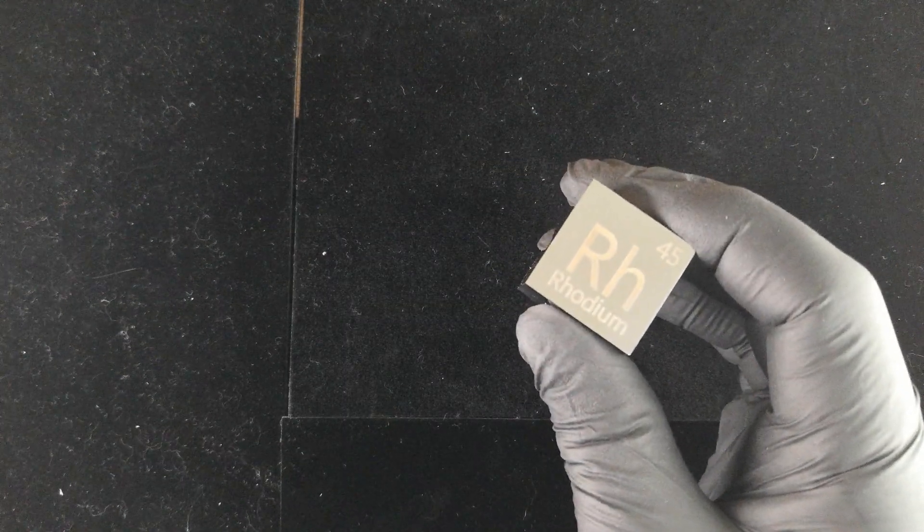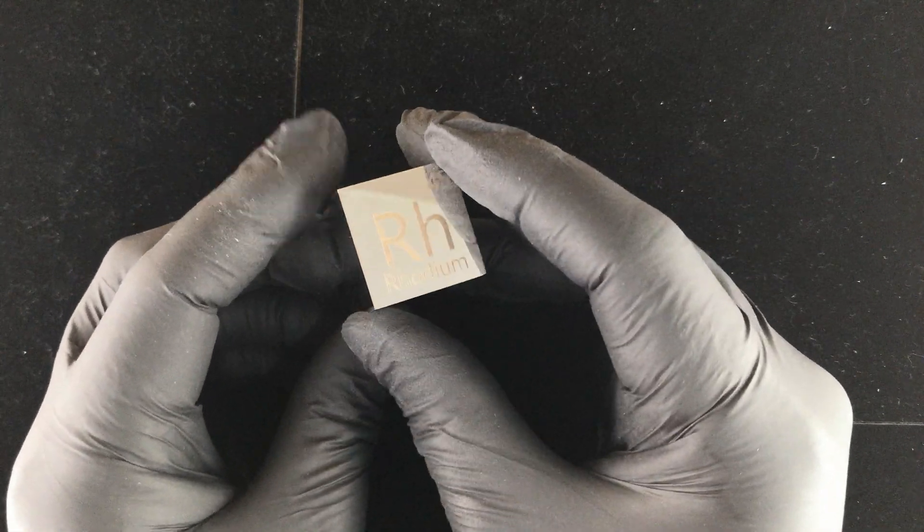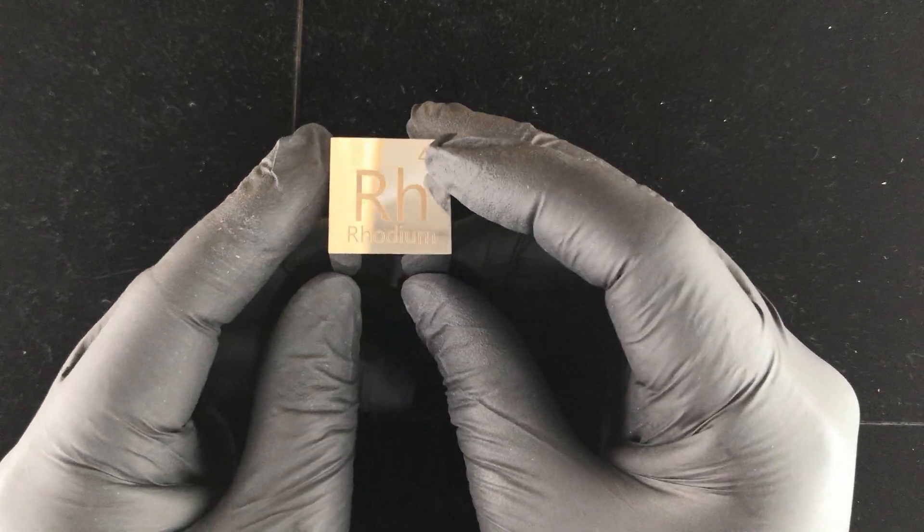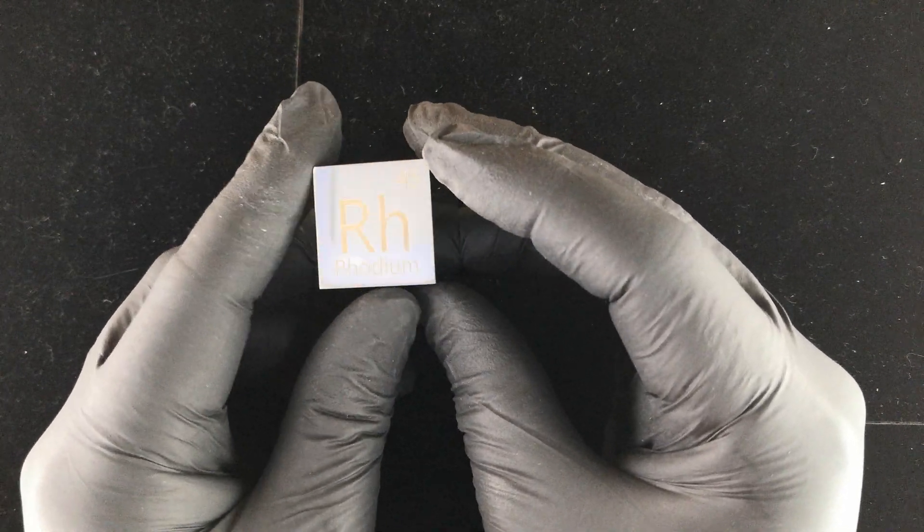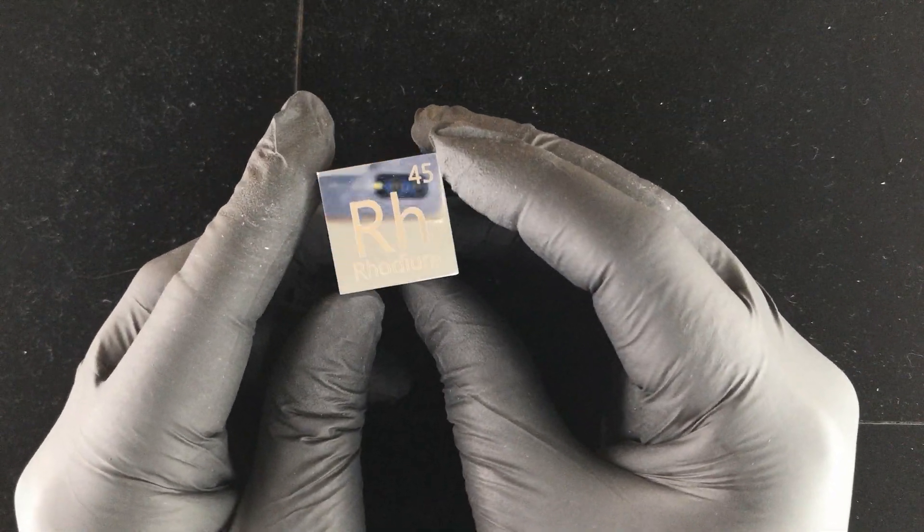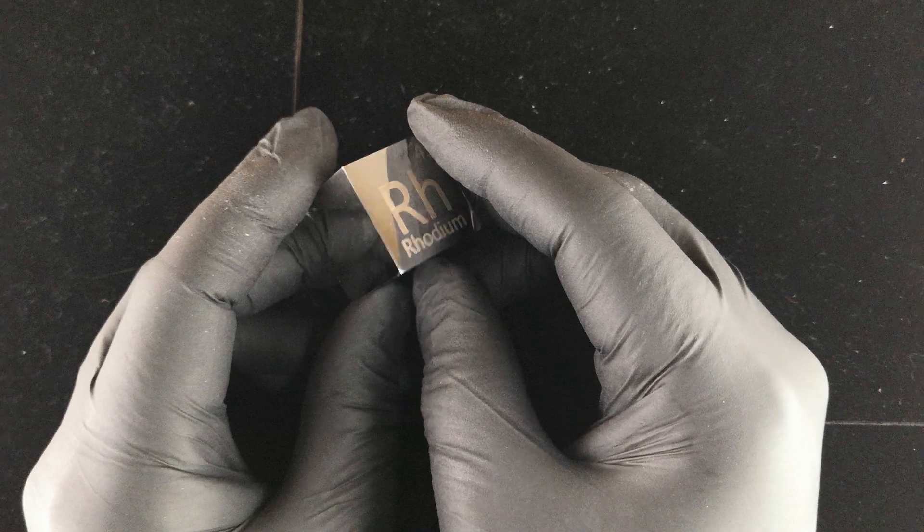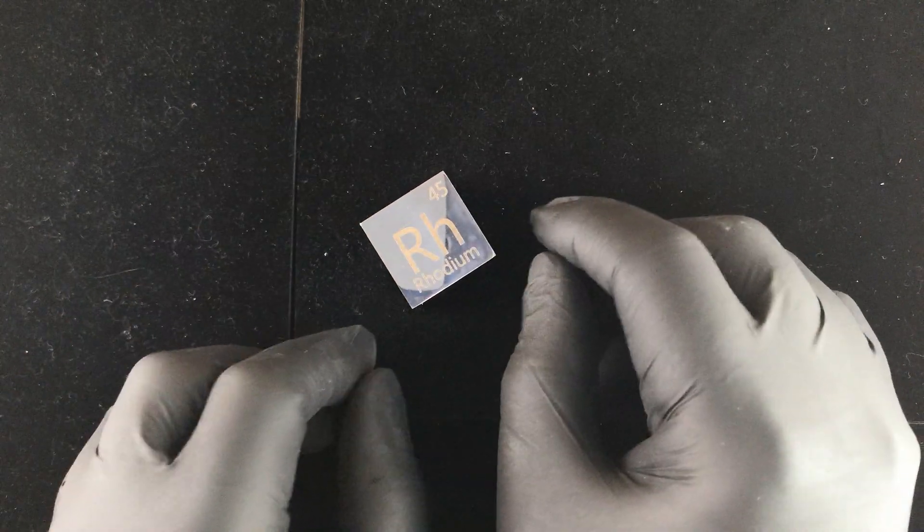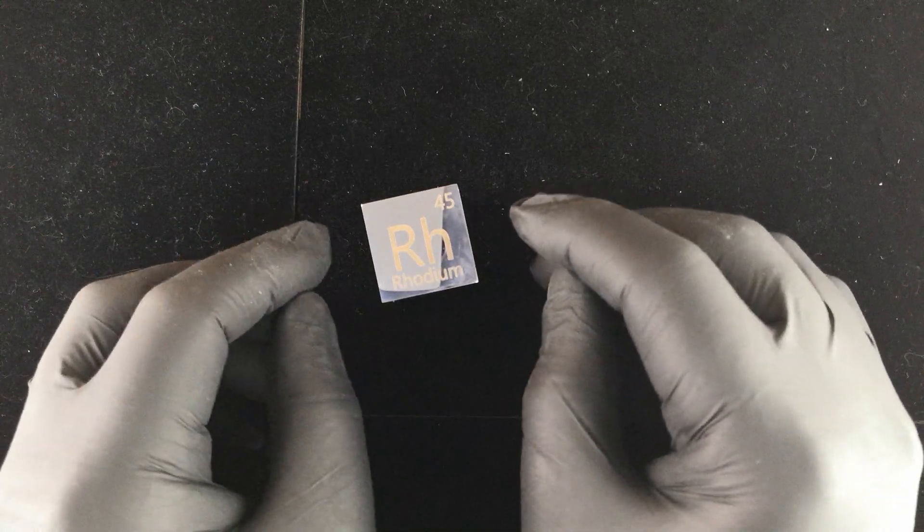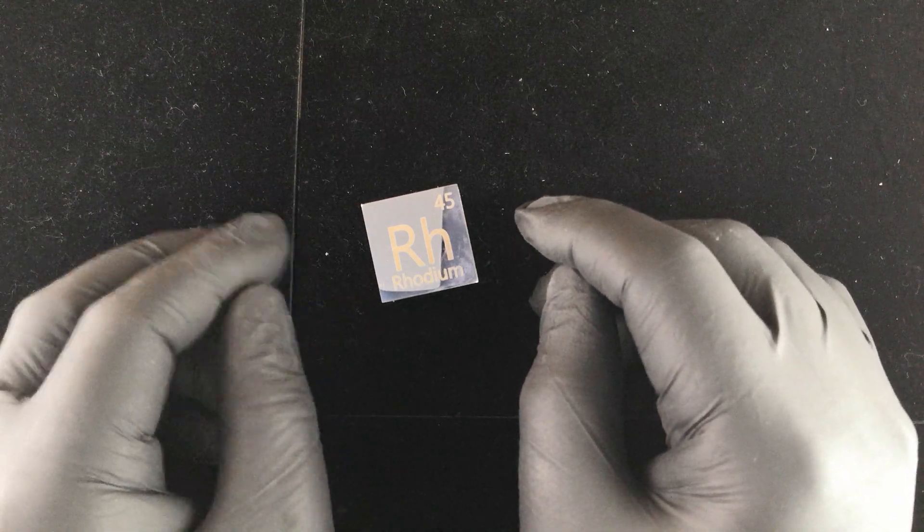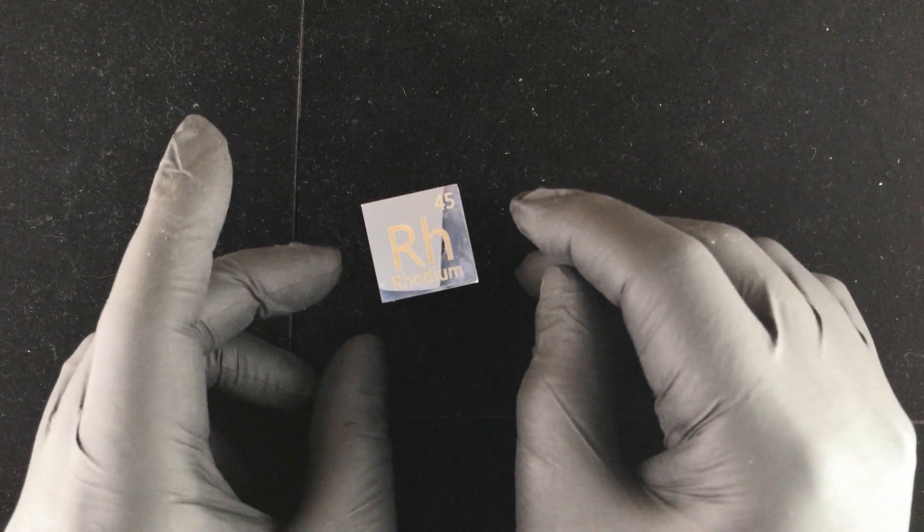But what's really the whopper here is the labor costs. What ended up happening is that the manufacturer had to order 255 grams to make the cube because in this process, it's not really melted, it's sintered. So, what happens is that the supplier will get a big bunch of the metal as powder and then press it under high heat to create a solid metal. And for all intents and purposes, it is a solid metal, but when you look at it under a microscope, you can see tiny little pockets that make it look more like a sponge instead of solid.